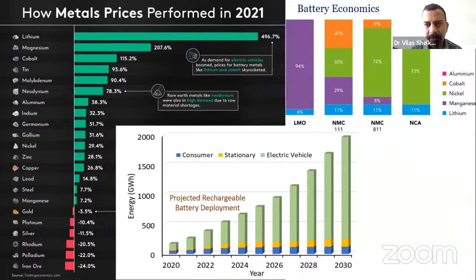So far so good, no issue with the battery. But if we see the economics of a battery, then this LMO battery has 6% of lithium and 94% of manganese. The NMC battery, which has a higher energy density, has 11% of lithium, 29% of manganese, 30% of nickel, and 30% of cobalt. Another variant of the NMC battery has 11% lithium, 8% manganese, 72% nickel, and 9% cobalt. These variations are basically made to increase the energy density, cycle life, and also to control the cost of a battery.